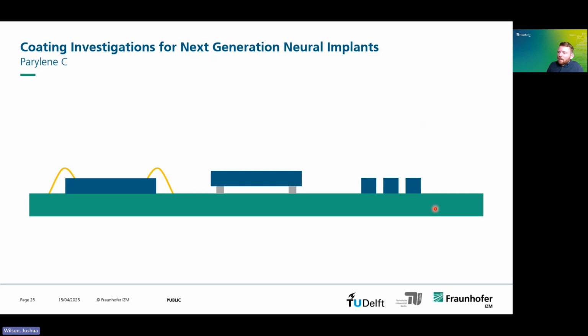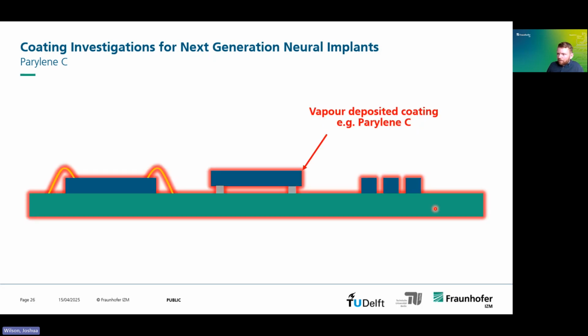The difference if you were using a vapor deposition technology is that the material is in the vapor phase inside the deposition chamber, and it condenses on the surface, and this condenses all over your device and can penetrate into very small spaces, and so this is what we're getting with a Parylene C.